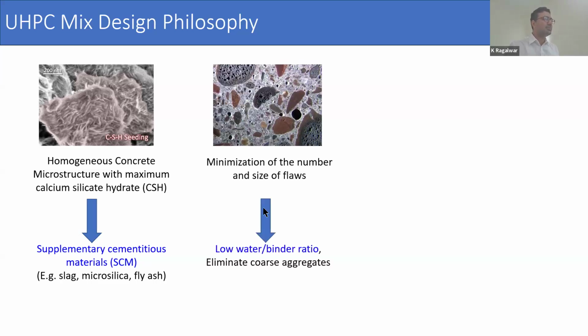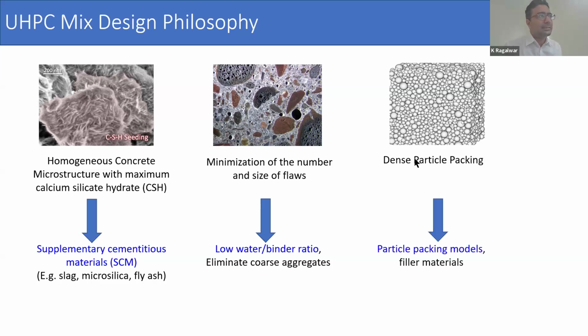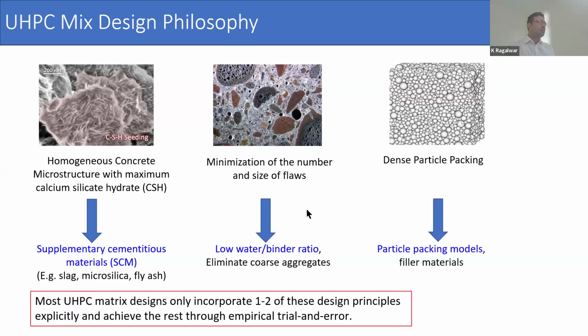Then the second point is minimization of the number and sizes of flaws. So that comes by lowering the water to binder ratios and eliminating coarse aggregate. And then the third one is dense particle packing. So dense particle packing also leads to self-consolidating behavior, which requires lower water to cement ratio and also eliminates any kind of flaws. So as I mentioned, most of the UHPC matrix designs only incorporate one or two of these design principles explicitly and achieve their target through trial and error method.